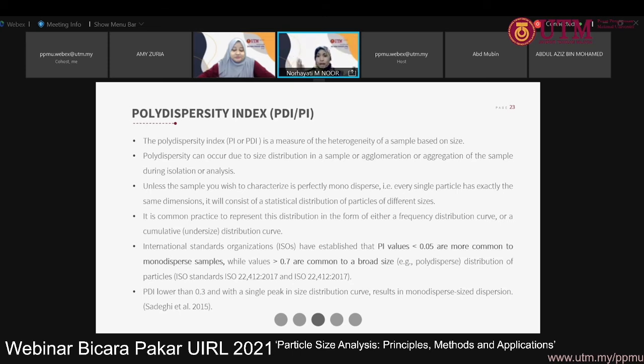And the smallest could be like 0.003. If you have a PDI value less than 0.05, it is very monodisperse, meaning every single particle is in the same size, you don't have big sizes. 0.05 is really small. Even for my formulation, it is difficult to get 0.05. But I'm targeting less than 0.3, which is quite enough. Some people say less than 0.5, so it depends on your area as well. You have to check with your applications.